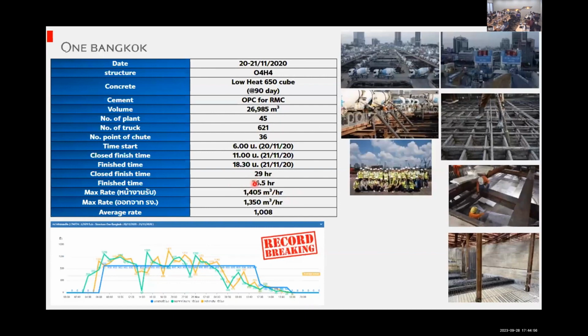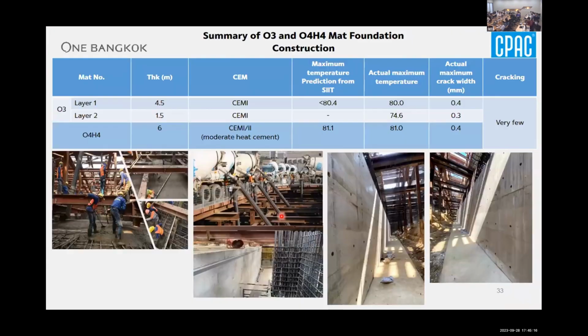We spent around 36.5 hours casting continuously. And the max rate of supply is around 1,405 cubic meters per hour, and average is around 1,000, something like that. So it's our pride project here. And after we observed the casting, we found some actual cracks, but it's very few. So it's acceptable for our party.